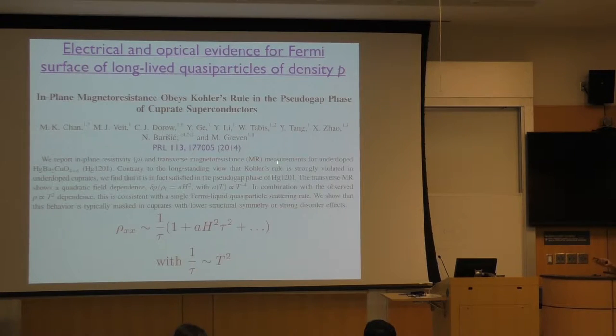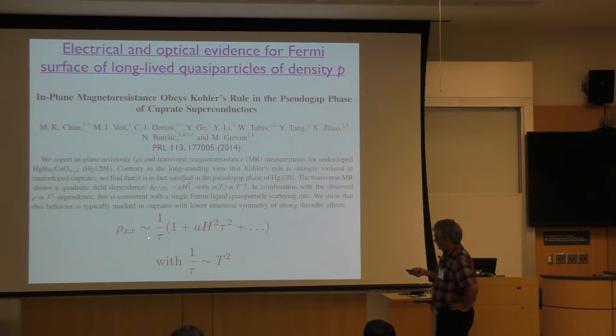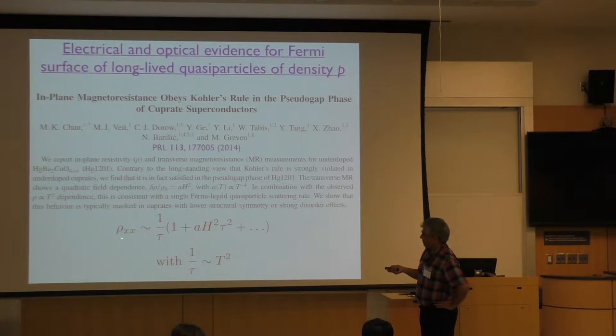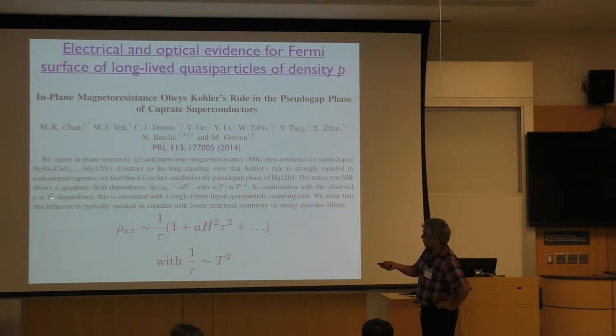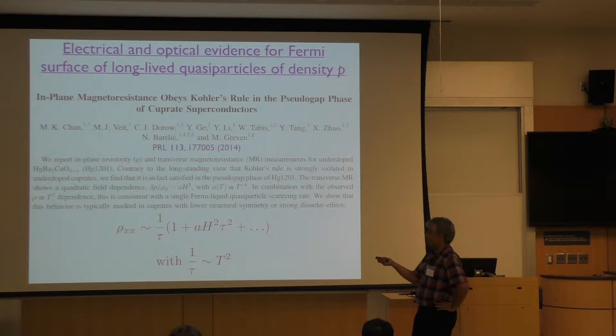More recently, there's work of Martin Greven who has looked at magnetoresistance — how the resistance depends on magnetic field and temperature. First of all, you find that rho_xx is 1 over tau, tau goes as T squared, so rho goes as T squared, meaning 1 over tau goes as T squared or omega squared. That's again what I showed earlier.